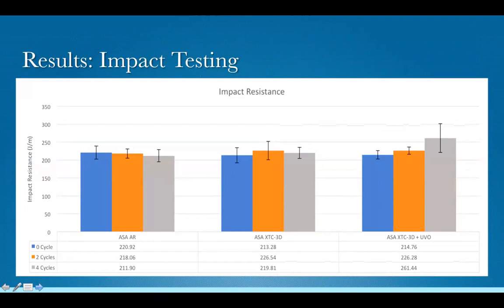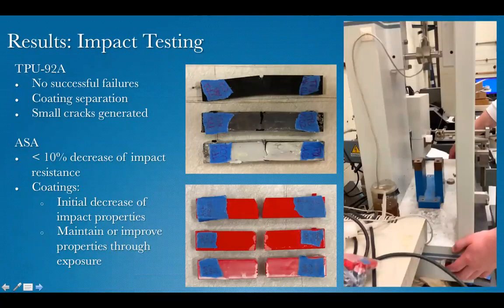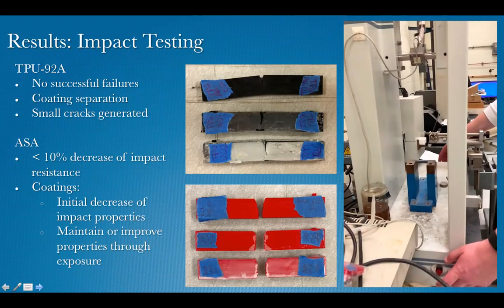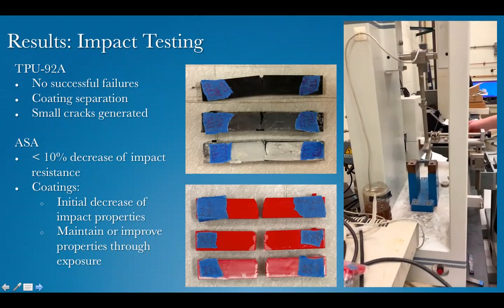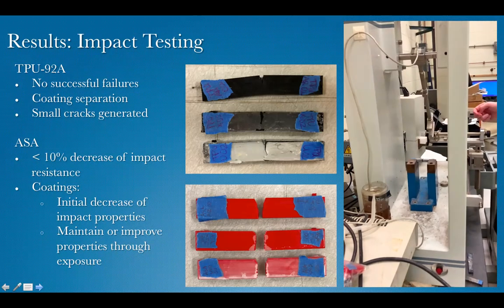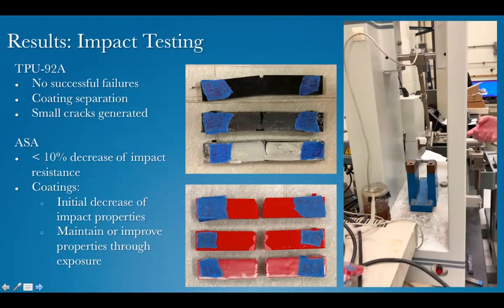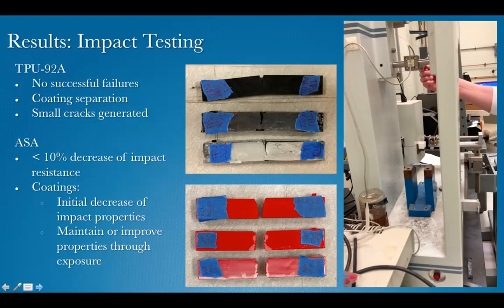The impact tested ASA fractured consistently within each time point and saw impact resistance values near 220 joules per meter. Both uncoated and coated, it saw a less than 10% decrease in impact resistance over the exposure cycles. The coated material, however, saw an initial decrease in mechanical properties from the as-received material, as was seen in tensile testing. The TPU-92A did not fracture through impact testing. Only a small crack was initiated below the notch on each sample. The coatings on the TPU-92A did flake off during testing.